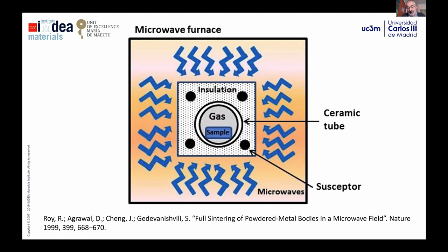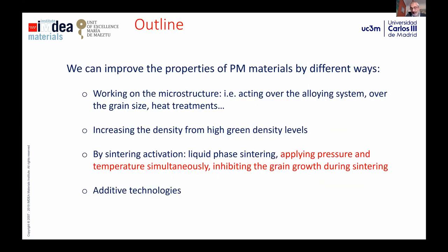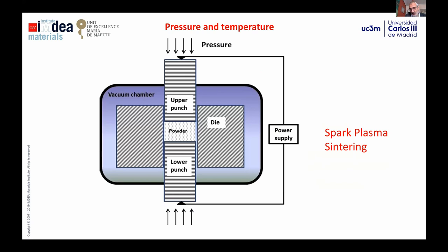Microwave sintering can reach very high temperatures in a very short time. That means that the dwell time for the sintering is not so high and you avoid the grain growth, and you can reach good microstructures with very fine grains without so much problem with this technology. But the most extended method in recent times to inhibit the grain growth, applying pressure and temperature at the same time, is the so-called field-assisted methods.